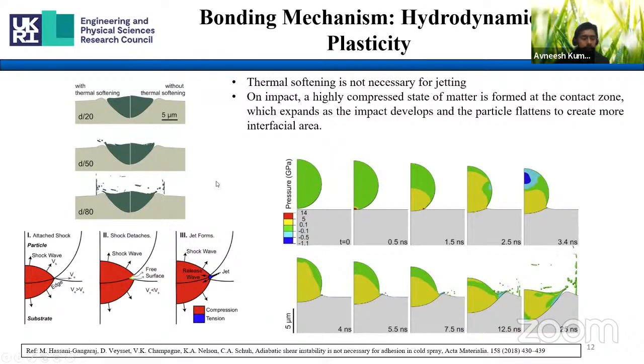For that, they are saying that when the particle strikes with very high velocity, a high pressure shock wave generates at the contact. These high pressure shock waves try to detach the particle from the substrate and take the jet out. To confirm that, they ran one simulation of a single particle without the thermal softening effect, and they said that on impact, a highly compressed state of matter is formed at the contact zone, which expands as the impact develops, and the particle flattens to create more interfacial area.